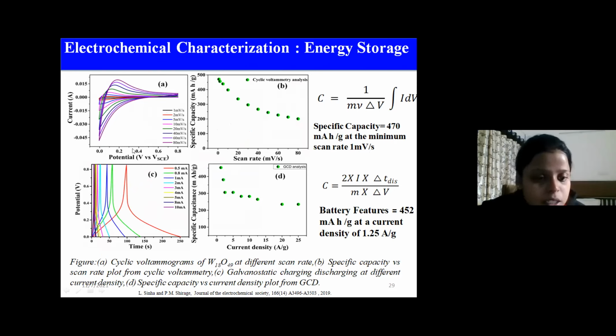Now we have conducted the galvanostatic charging discharging measurement so as to know the charging discharging properties of the material, and it is approximately 452 milliampere hour per gram at a current density of 1.25 ampere per gram. So from this GCD and cyclic voltammetry curve, we can see that the material is giving properties of pseudocapacitive battery nature.